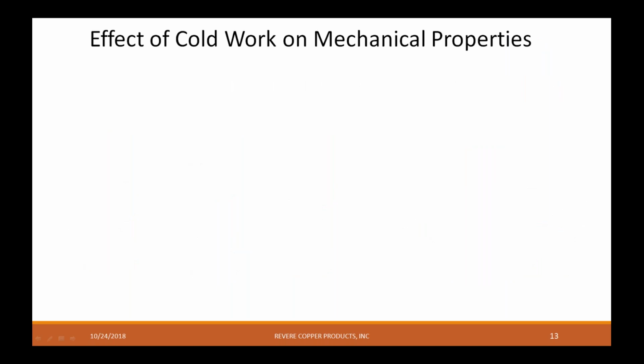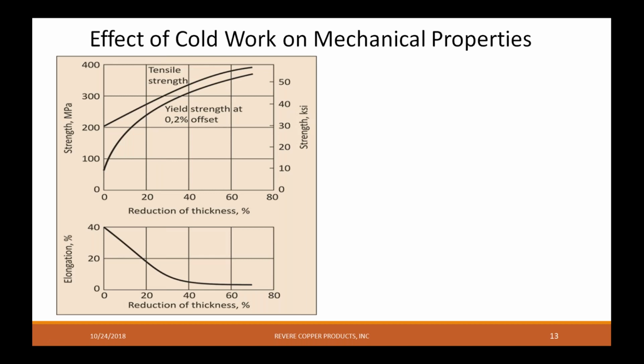So what happens to the metal mechanically while you're rolling it? So as we mentioned earlier, you make it stronger. You add strength to it by deforming those crystals. So that top slide shows an increase in tensile strength as you reduce the thickness. So let's say you started with a piece of copper that was a 1/2 inch thick roll of it, and you rolled it down to a 1/4 inch. You did a 50% reduction. Your tensile strength would go from about 200 up to, it looks like about 350.